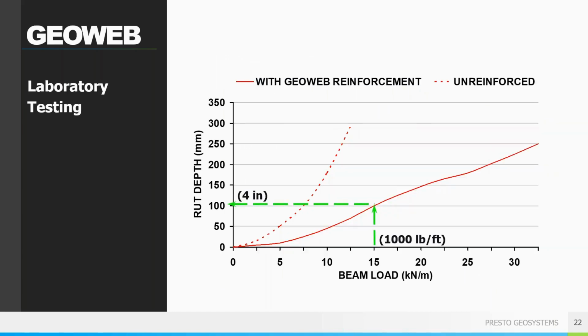We compared this to the same depth of unconfined aggregate. So the peat pit test showed that bases reinforced with GeoWeb provide a significant improvement over unreinforced soils. For a loading of 1,000 pounds per foot, a 4-inch rut depth occurred with GeoWeb in the section compared to 20 inches without the GeoWeb.